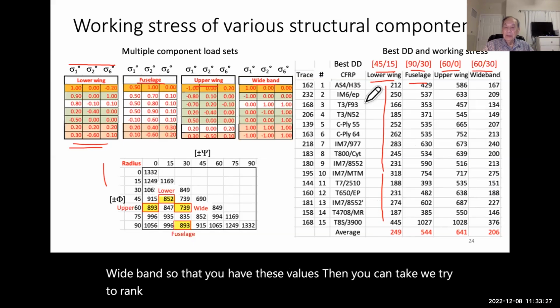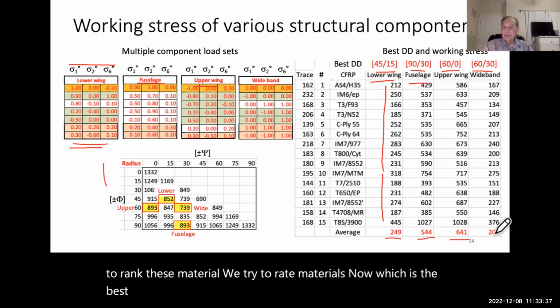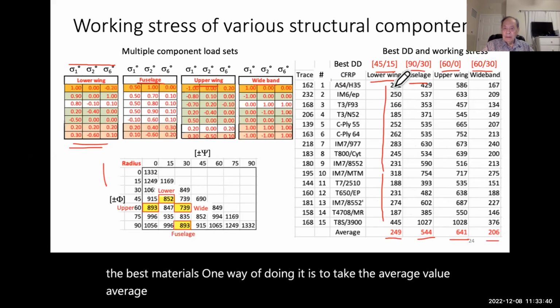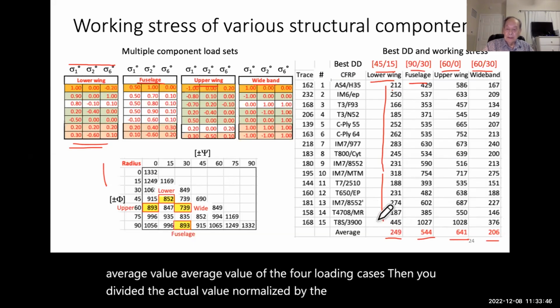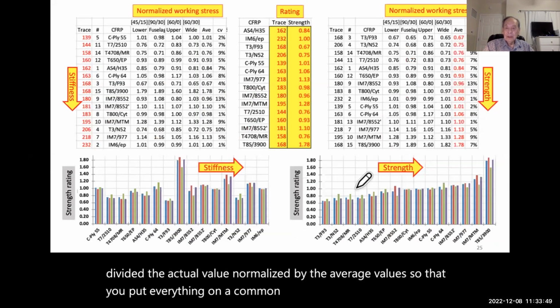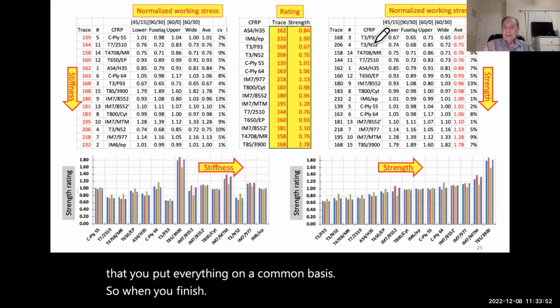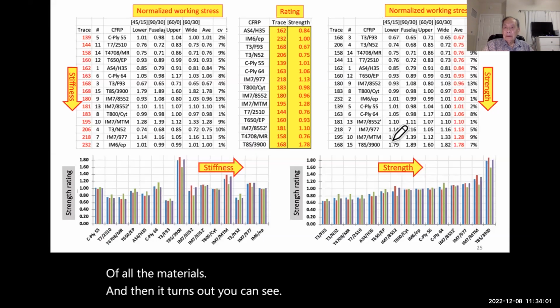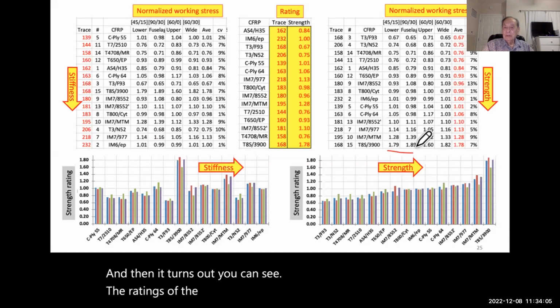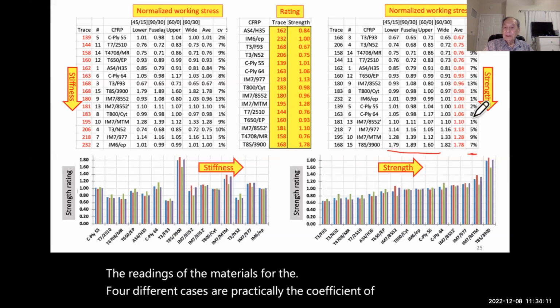We try to rate materials now. Which is the best material? Well, one way of doing it is to take the average value of the 4 loading cases. Then you divide the actual value by the average value, so that you put everything on a common basis. So when you finish, here will be the case of all the materials. And then it turns out you can see the ratings of the materials for the 4 different cases are practically the same. The coefficients of variation are indicated in here.